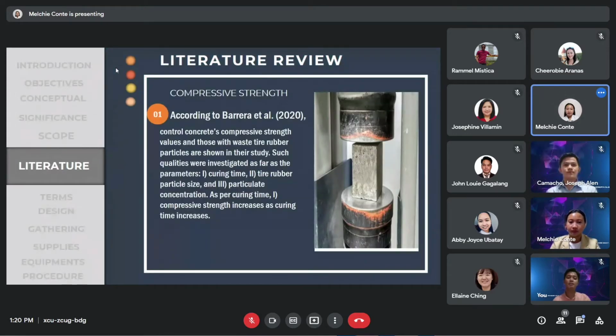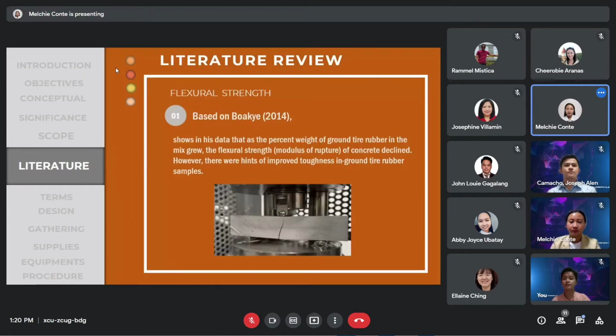For compressive strength, based on the case study entitled Waste Tire Rubber Particle Modified by Gamma Radiation and Their Uses as Modifiers of Concrete, conducted by Barrera, Diaz, Rabanal, Gayare, Lopez, and Olivares, concrete's compressive strength value is compared with those with waste tire rubber particles. Such qualities were investigated as far as the parameters: curing time, tire rubber particle size, and particulate concentration. As per curing time, compressive strength increases as curing time increases. As per particulate concentration, compressive strength value gradually decreases when the particulate concentration increases.